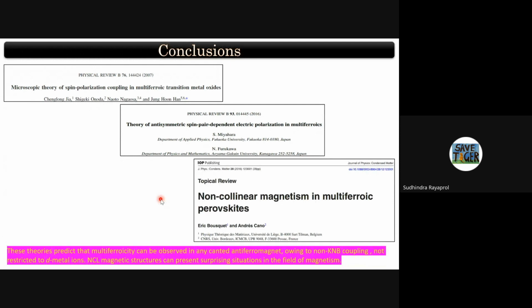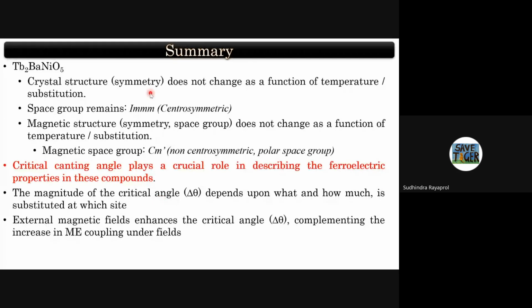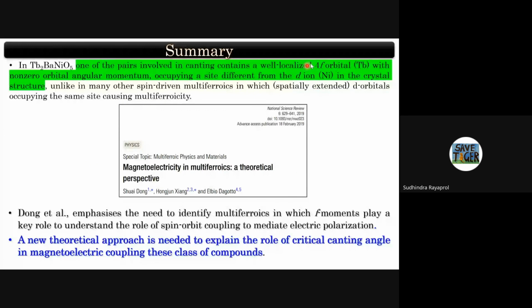So that is something which we were able to bring out from our neutron diffraction results, that the magnetic structure can play a major role in explaining the physical properties of our systems. This is the summary of this part: a critical canting angle plays a crucial role, which opens up the question of the role of the 4f orbitals, which results in a non-zero angular orbital magnetic moment, which interacts with the different 3d ions. It can be nickel, it can be cobalt, and because of this interaction, we see a canting of the spins, and the difference of this canting angle gives rise to the magnetodielectric or magnetoelectric effect in these compositions. So the role of 4f orbitals needs to be included in the theoretical approach, and that was the major conclusion of our work.